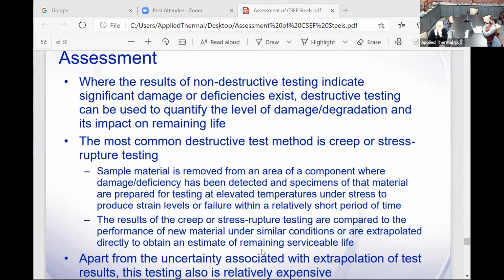There's some additional things that can be done. Just cover this real quickly here. The results of non-destructive testing indicate significant damage or deficiency. Destructive testing can be used to quantify the level of damage and the impact on remaining life. The most common destructive test method is creep or stress rupture testing.